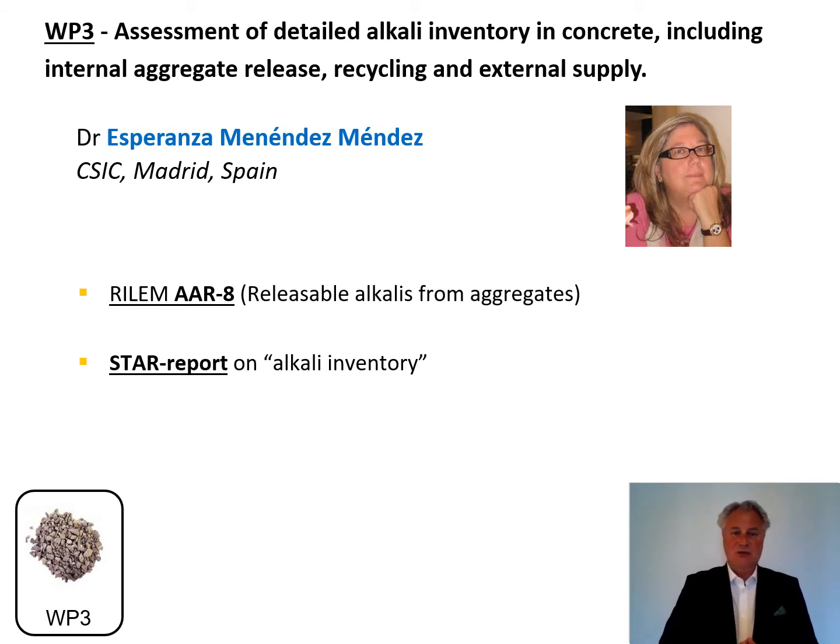So a new test method was developed, the RILEM AAR-8 method. We made 2 round-robin tests, and we now have this RILEM AAR-8 method measuring the potential maximum releasable alkalis from aggregates in the laboratory. That is a very interesting method, but it's very important to tell that this is an accelerated method in the laboratory, and we do need to verify the results coming out from this method and the number itself. In addition, in this work package we made a STAR report on the alkali inventory.